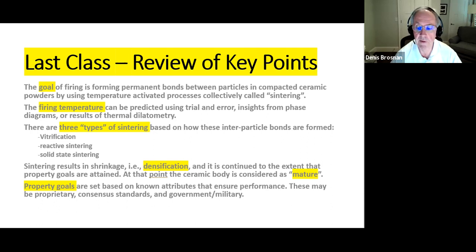A more enlightened approach is to use phase equilibrium diagrams, maps that show when processes will take place. We can make educated guesses because usually in ceramics, the processes are at the point that the furnace interior is glowing red. We've achieved red heat, which is above 900 degrees Celsius. Another way to do this, in a much more enlightened way, is to use thermal dilatometry, not to determine thermal expansion coefficients, but to look at the point where shrinkage starts in the ceramic under the action of heat.